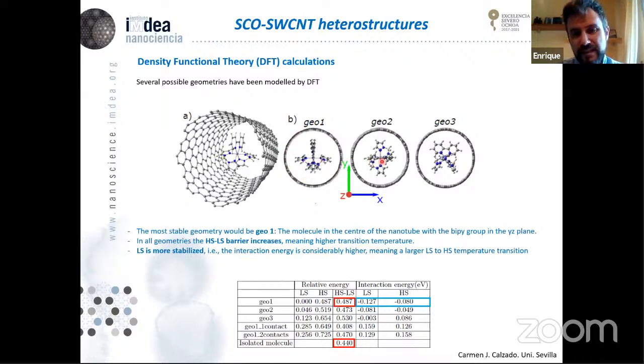But apart from that, there are several configurations in which the molecule feels more comfortable with not so much energy difference. The relevant thing for us is that when she calculates the relative energy between high spin and low spin state, what she gets is that it is in general higher than when the molecule is isolated or in crystals. So this would in general tend to push the critical temperature to higher temperatures.